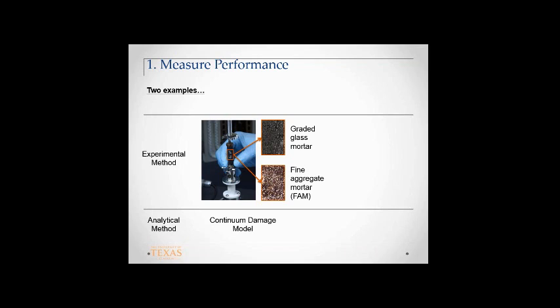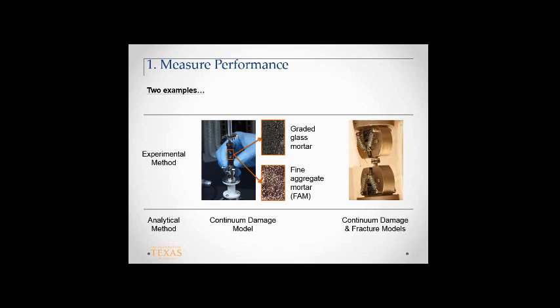There are models, we've looked at several models, including continuum damage models, that can very easily be applied to this kind of system to characterize fatigue, healing, and so forth. Another approach is what we call a poker chip test. Poker chip test is basically a sandwich, a thin film of asphalt binder sandwiched between two rigid plates here, and you can do this in transverse mode, you do this tensile test. Both of these tests try to test the binder by subjecting it to a stress state that is more realistic in terms of what the binder would see in an asphalt mixture. Okay, that's the whole idea.